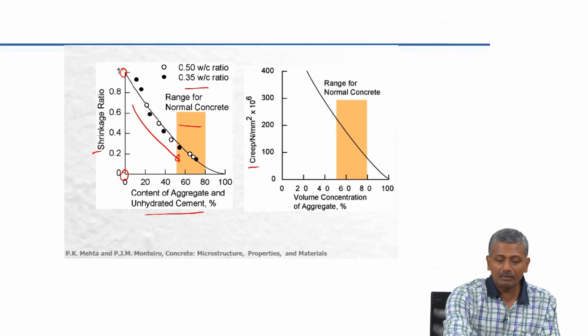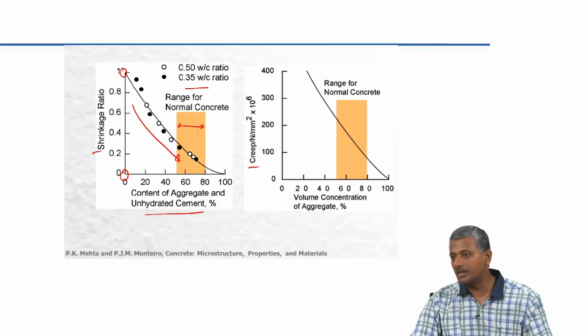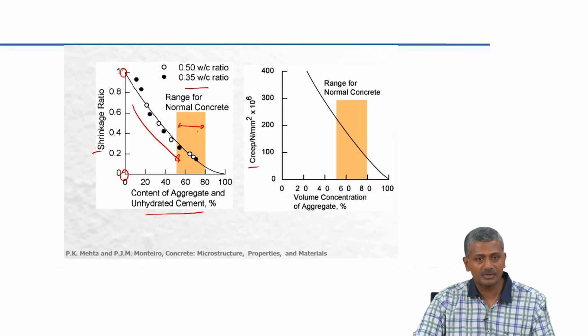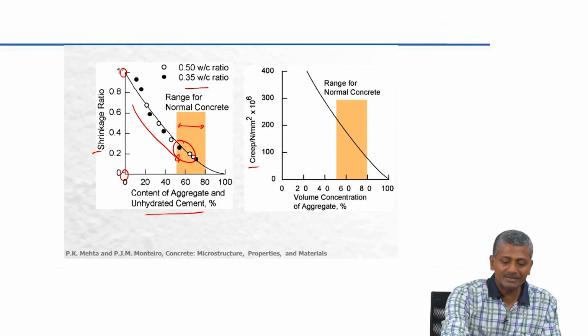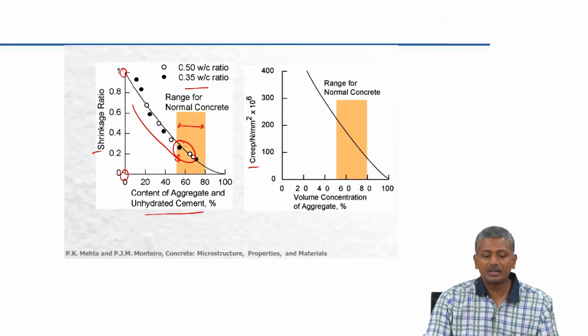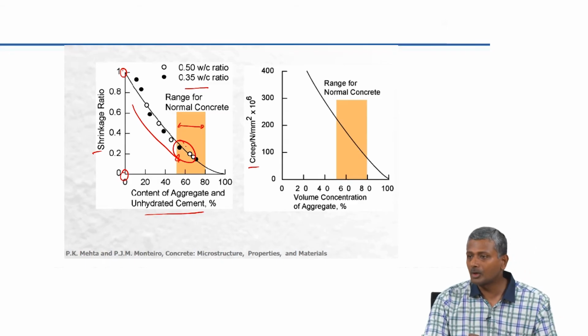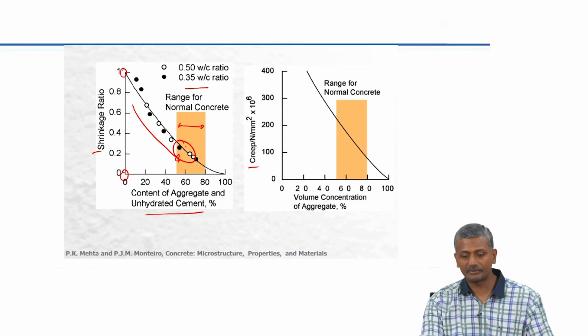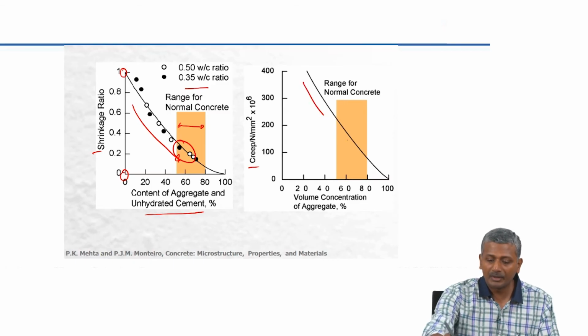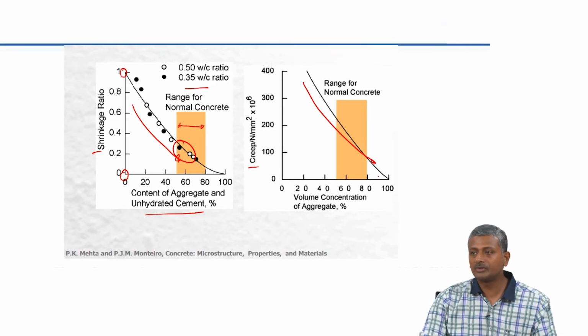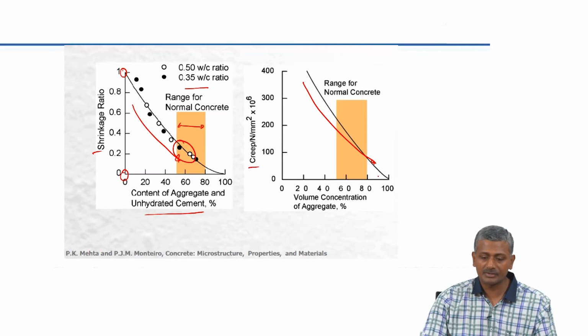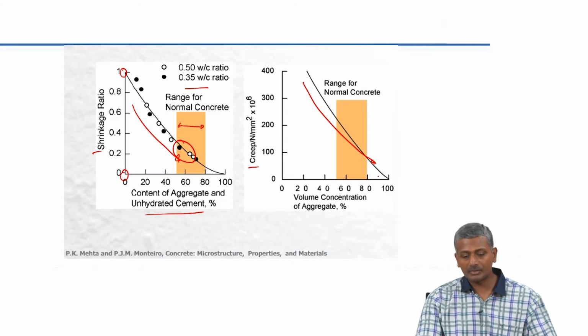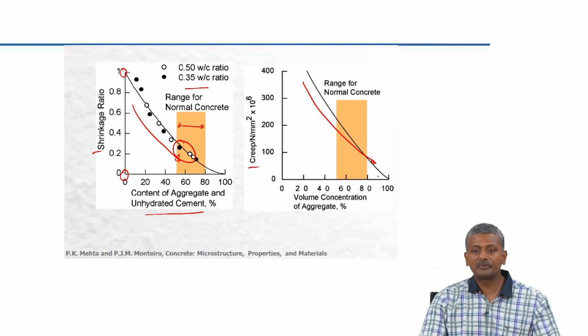The range for normal concrete is given here. Typically, we have 60 to 80% aggregate content in your concrete. So, if you look at the extent of shrinkage, we are talking about shrinkage of concrete being about 20 to 30% of the shrinkage of cement paste. Okay. Shrinkage of concrete is about 20 to 30% of shrinkage of cement paste. Creep on the other hand, again decreases significantly with respect to the increase in aggregate content of your system. For normal concrete, your creep can be 25 to 35% of your overall creep of the paste.